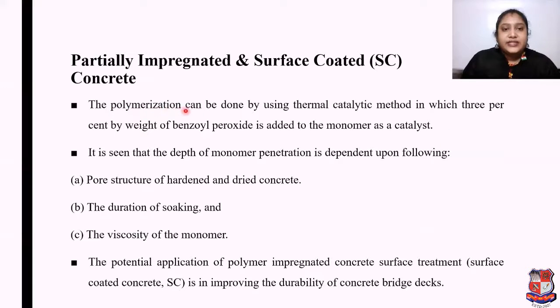The polymerization can be done by using the thermal catalytic method in which 3% by weight of benzoyl peroxide is added to the monomer as a catalyst. It is seen that the depth of monomer penetration is dependent upon the following: pore structure of hardened and dried concrete, the duration of soaking, and the viscosity of the monomer.